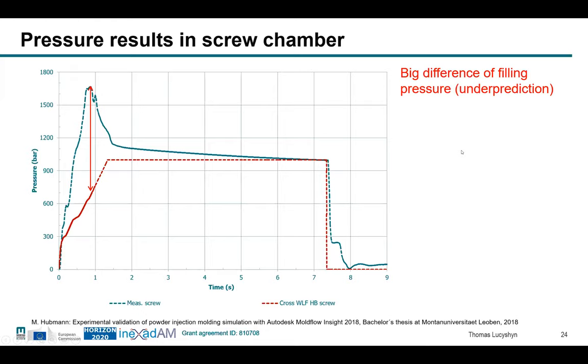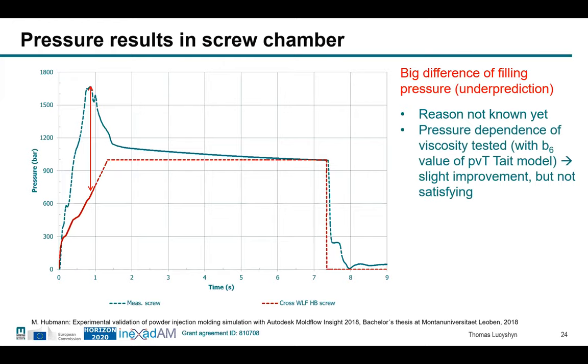There is still something that is perhaps happening inside the converging flow of the nozzle. We also had a look at the pressure dependence, which is not originally measured. So pressure dependence is always like an add-on of your rheological characterization. So we didn't measure it, but we tried with this coefficient. You can use one coefficient of the PVT model, which can then be used in the rheological model as a starting point if you don't have the real measured values to see the influence. And it showed a slight improvement. So the simulated pressures were higher, but still far away from the reality.